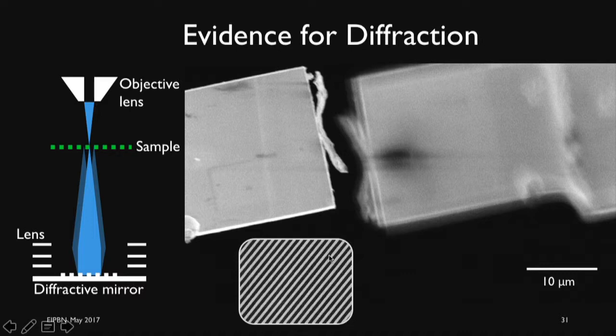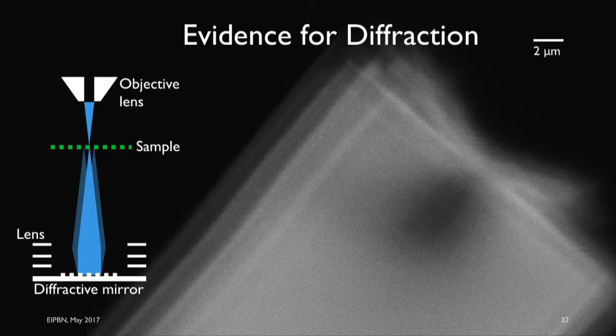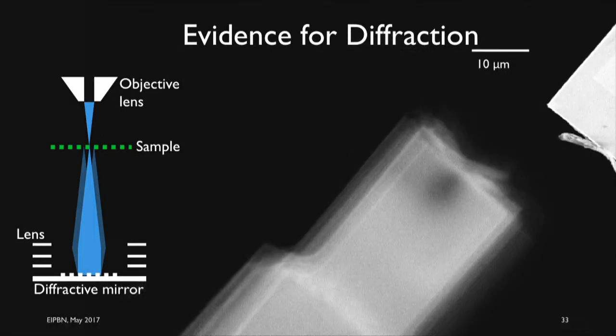The point of looking at the orientation of the diffraction grating is the fact that we know the diffraction spots should show up along a line orthogonal to the direction of the diffraction grating. And in this case, you see they actually do. This direction is orthogonal to the direction of the diffraction grating. However, here's another example. You can see these repeated, fairly sharp lines showing up, and this is again evidence for diffraction. If you zoom out a little bit, you see that it's not only on one side. These lines are showing on both sides of the reflected image, which you would expect because we have not only positive orders of diffraction, we have the negative orders of diffraction, and they would all contribute to these repeated images.